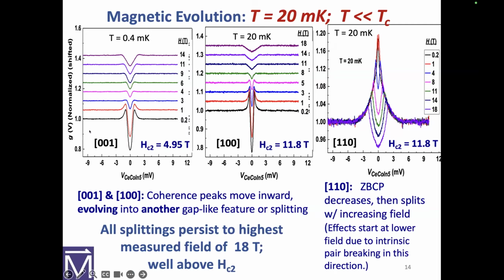So here we have the 001 C-axis direction. We're sitting down at 0.4 milli-K, and HC2 in that direction is about 5 Tesla. So here we are, with just enough field to drive the lead normal. We have here the cerium cobalt indium 5, and the black is the tunneling density of states. I'm not using the laser pointer because I can't keep track of it. Now we're slowly going up in field in Tesla: 1, 3, 4, 6. 6 Tesla is here, and we see this structure slowly changing and broadening.